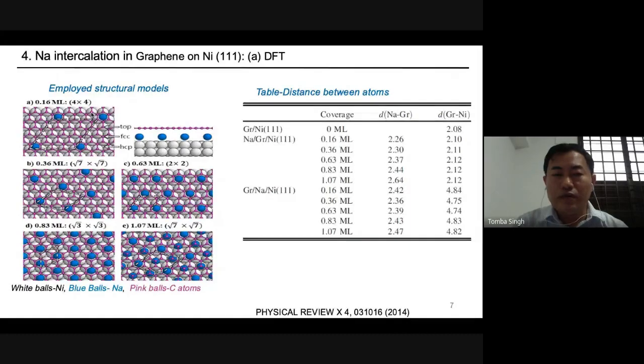Here, the carbon atoms of the graphene hexagon want to sit at the top and FCC sites of the substrate. Now, the HCP site remains vacant, unoccupied. This falls at the center of the graphene hexagon. So if we introduce metal atoms, they like to sit here. They start sitting here at low coverage. As we start introducing them, the unit cell is shown by this white dashed line.